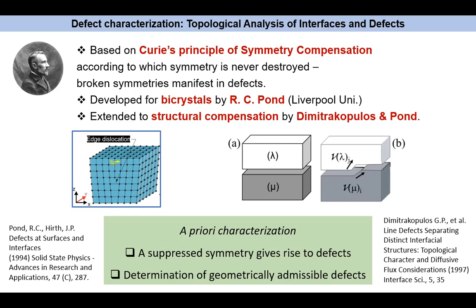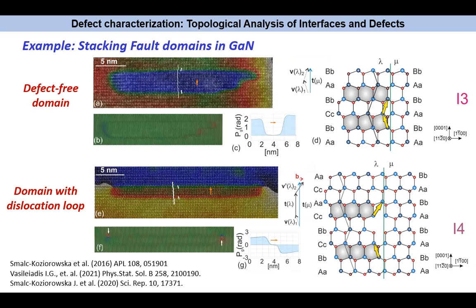In other words, suppressed symmetry gives rise to defects, and also structural operations within the unit cell may give rise to defects. And then we can have a knowledge beforehand of the geometrically admissible defects in a material. And here is an example of a recent application of this theory regarding closed domains that are formed by the overlap of stacking faults in gallium nitride. Depending on the sense of the overlapped stacking fault structural units, you can have a closed domain that is defect-free, or you can have a domain that is surrounded by a partial dislocation loop that is very similar to Shockley partial dislocations.